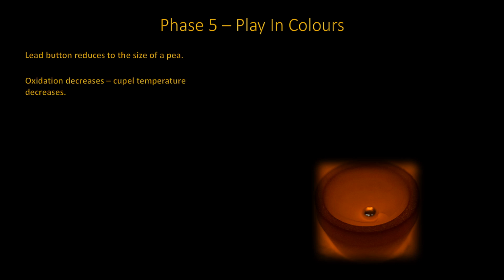If things go well, nearing the end of the process, that alloyed bead of lead and precious metals will be reduced to the size of a pea. Oxidation decreases, and so does the Cupel's temperature. At the same time, any gold, silver, or platinum group metals that may exist will become concentrated in that small bead. The remaining lead becomes more difficult to oxidize and the remaining metals to fuse.